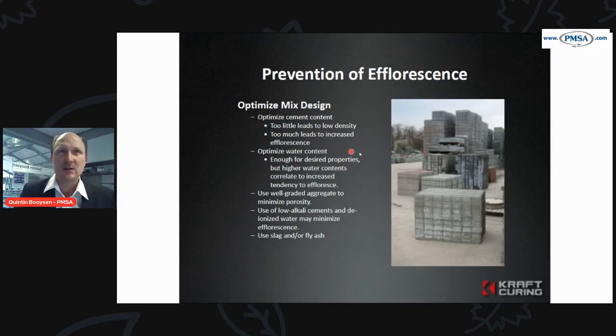Optimized water content. So enough for the desired properties. The water content needs to be correlated to the cement. So if you have too much water, you're going to have a lot of free water that's not bonding with the cement particles through the hydration of the cement. So you're going to have more free water, which will obviously ultimately create little gaps within your concrete, and that will be a transfer mechanism for the calcium hydroxide to start moving through your concrete.